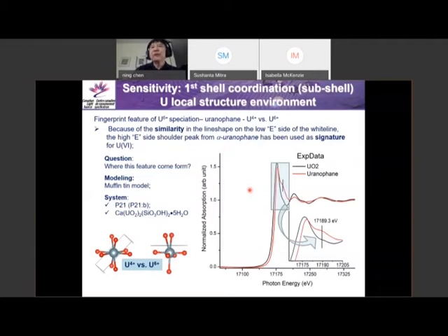For example, right now we have a mineral system. When you go to the synchrotron, the very important information you want to get is redox. So for example, you want to look at 4+ versus 6+ redox. You want to determine whether these two coexist, and what the partitioning ratio between them is. And then I picked a very difficult case. If you're looking at the relative yield case, 3+ versus 2+, or whatever, those would be very easy. I picked a difficult case here.